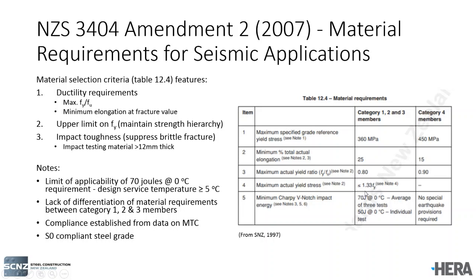The reason for this is that we're trying to maintain the strength hierarchy that was assumed during the capacity design approach. So in 3404, there's some material overstrength factors which are based on material variability of historic steels. We want to make sure that the steels aren't too strong and that we invalidate the capacity design approach and end up with actually yielding our columns rather than protecting them.